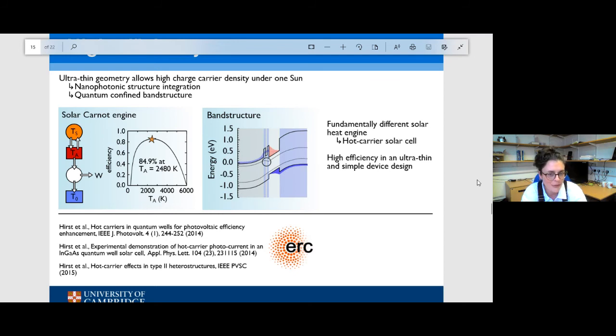And I'm sure many colleagues will be familiar with this concept for investigating non-equilibrium effects in novel materials using ultra-fast spectroscopy. But actually, we know that we can generate those same charge carrier densities if we're smart about it with continuous illumination, particularly if we use things like quantum confined band structure to really force the carriers just into one space and to force them to stay there. What does this do? Well, by maintaining a hot or an energetic population of carriers that don't so readily dissipate their energy to the surrounding lattice, we potentially allow ourselves to obtain higher efficiencies. And in the ultimate case, a solar Carnot engine, which is what you see here. It's really the thermodynamic dream of photovoltaics. And it certainly is a dream at this point.